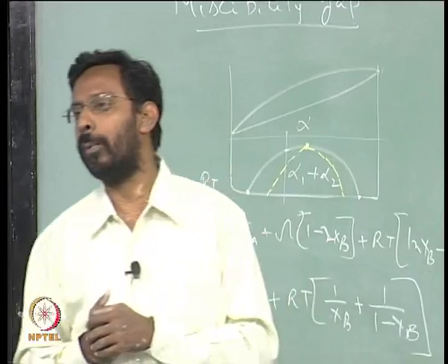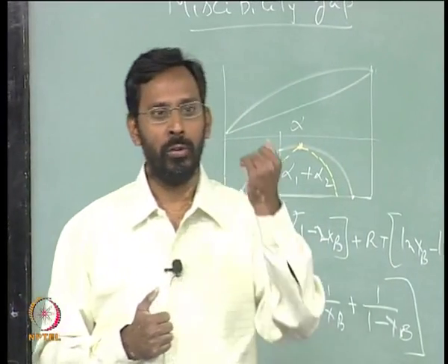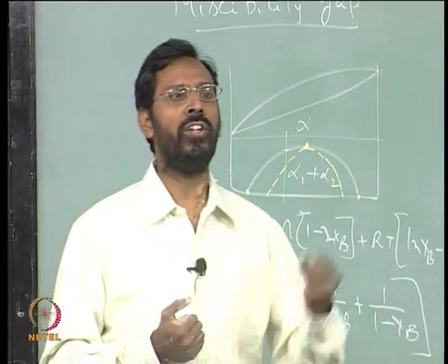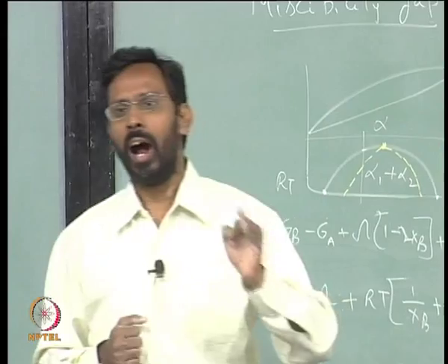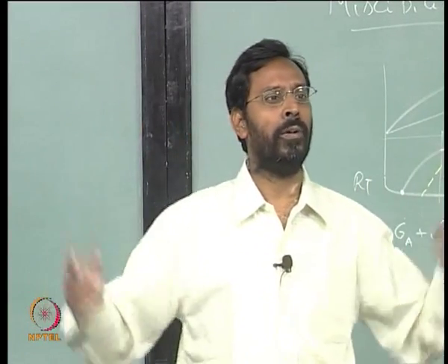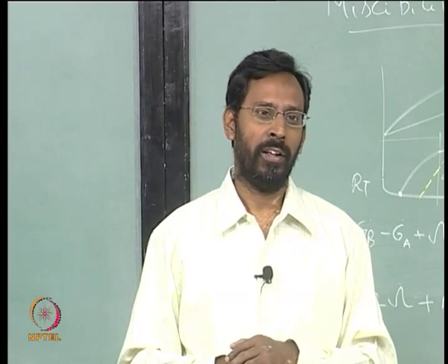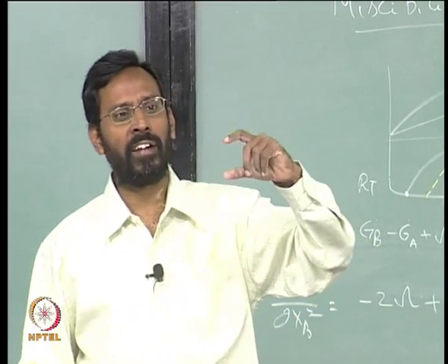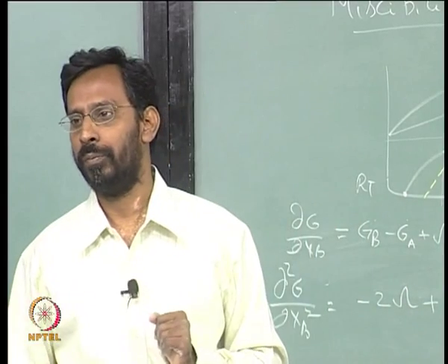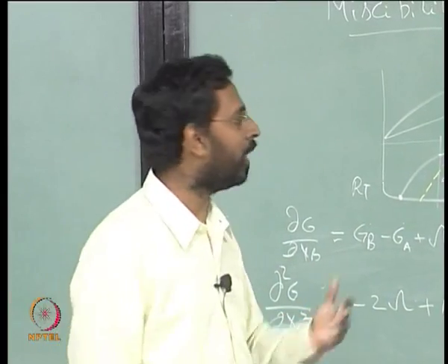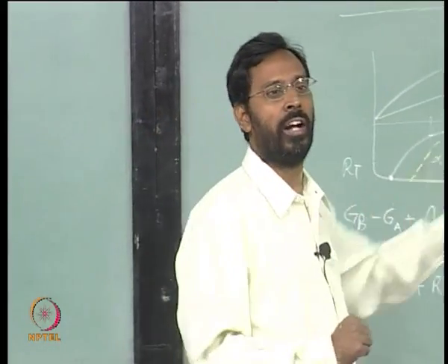If I take gold copper, Cu-Au, you have 3 compounds we talk about, AuCu, Au3Cu, Cu3Au. That means at 3:1, 1:1 and 1:3, these 3 compositions you have an intermetallic suddenly, at no other compositions you have. That means at other compositions the interaction between A and B is not as strong as at these compositions. So that basically tells that omega is not really constant at all compositions.